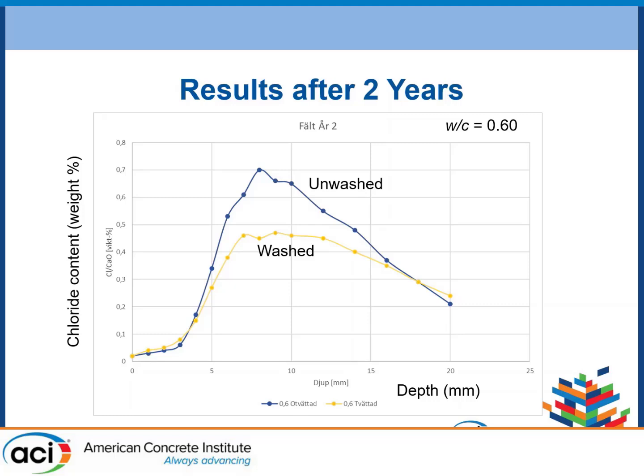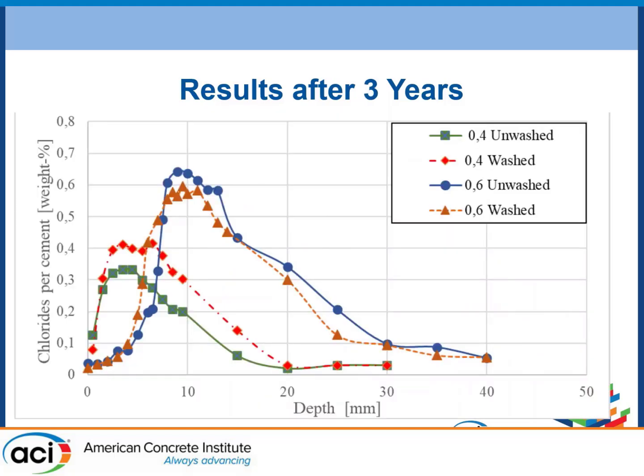And then you can see that we measured after 2 years, there was a rather good difference between washed and unwashed, if you look at the chloride content. It is measured at depth, and you can see that the highest value is a little bit from the end of the structure. Also, in the case where it's not washed, you still have the rain, which is a natural way of washing. For the modern concrete the difference was much smaller. And here you can see after 3 years, there is hardly any difference, just a minor improvement. So we were a little bit disappointed, of course, as we had anticipated a greater difference.